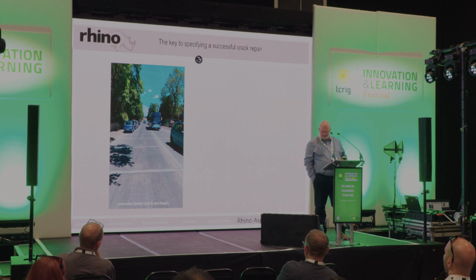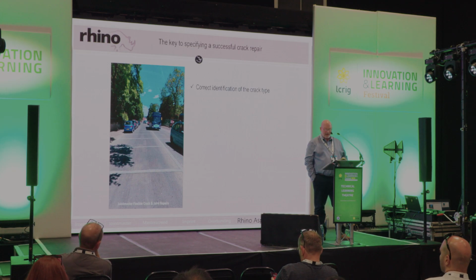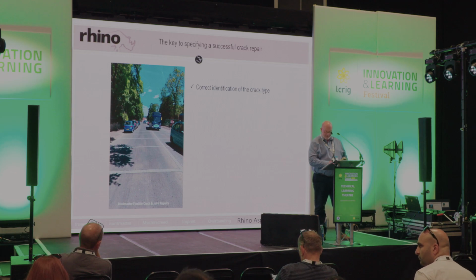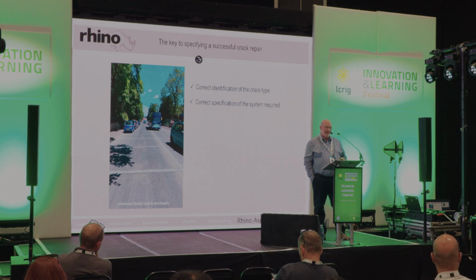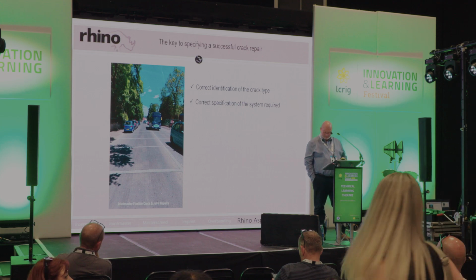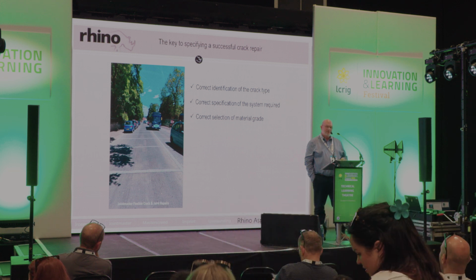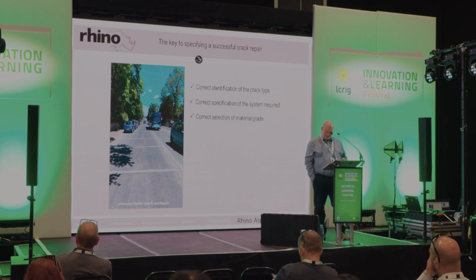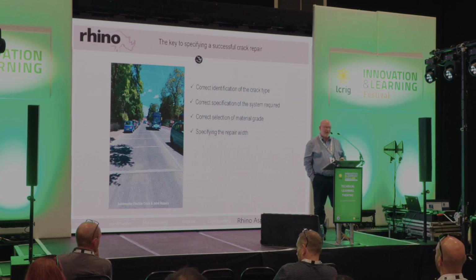So the key to successful specification of a crack repair: you need to identify the type of crack that you've got on the carriageway, the correct specification of the system, whether it's an inlaid or an overband system, the correct grade of material, whether it's a low or a high modulus repair, specifying the crack width. Again, I would reiterate, specifying the repair width, not the crack width, and specifying the depth of repair needed as well.